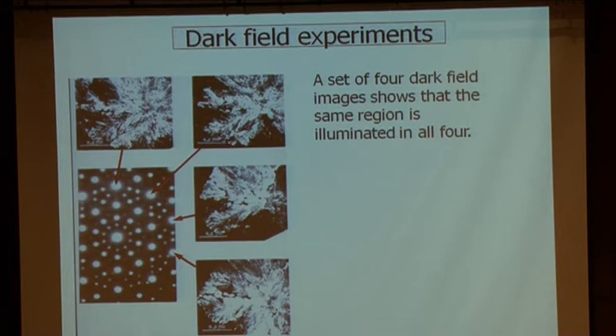When it goes through, at certain angles, it will diffract. So beams will come in each and every direction, and also there will be a transmitted beam and diffracted beams in different directions, okay? Underneath, there's an aperture. Aperture is a piece of metal with a hole in the center. High-tech, piece of metal with a hole in the center. And that aperture allows one beam to go through. So what you can do, let's say that these are the beams in one direction. We have these and so on. Let's say that this is the transmitted beam. If you allow this beam to go through, then you get a bright field image formed. But if you tilt the beam so as to allow this beam to go through, then you get a dark field image.